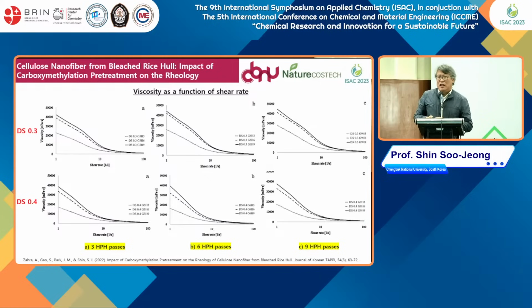Most research on the carboxymethyl pre-treatment method is focused on DS.1. Other research groups use DS.1, and commercial carboxymethyl cellulose is focused on DS.6 to DS 2.0. Because less than DS.6, it's very difficult to make the fibrillation by blender or low mechanical treatment. So my research group is focused on between DS.2 and 0.6. There are very different kinds of rheological and mechanical properties that come from these things.